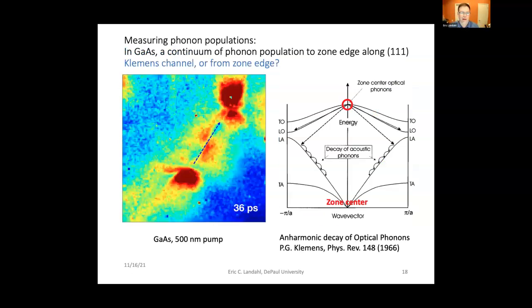The Klemens channel, or the filling in of the LA branch, sort of mid-zone, presumably from zone center, that was observed by David Reis's group in bismuth, is also seen in our data, but it happens a little bit later, about 30 to 40 picoseconds in the case of gallium arsenide. And so this long-expected anharmonic decay channel, we also directly confirm via diffuse scattering measurements. Of course, we can't really say what the source of those phonons is, whether it's the zone edge or in fact from zone center. All we do again is view where they are, not where they're coming from.